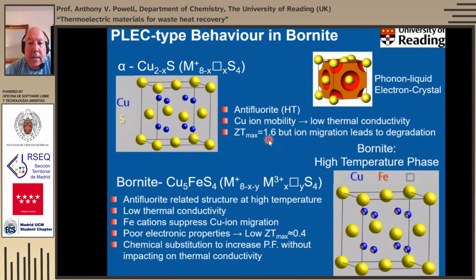However, ironically, it's that ion migration that leads to these materials degrading in use, because if they're subjected to a temperature gradient and have liquid mobile copper ions, and there's also a potential difference being generated, you'll get copper ion migration, and it's seen that copper starts to plate out on one face of the thermal elements under sustained operation. And of course, then the performance degrades. So what we wanted to do is we wanted to try to stop that migration.